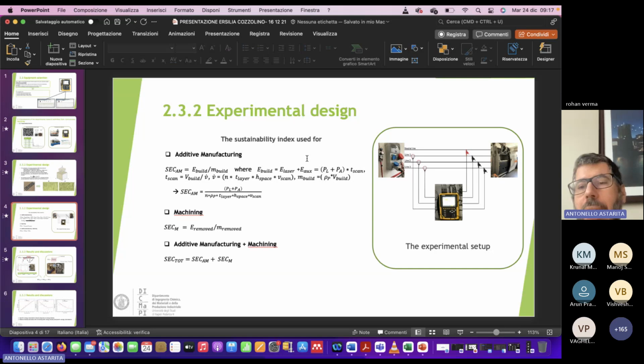So another good point is trying to reduce the processing time, because by reducing the processing time, you both increase the productivity of your system and decrease this amount of energy. Again, you can calculate these two amounts as the power required by the laser plus the power required by the auxiliary system, both of them multiplied by the scanning time, so the production time. But how to write down the scanning time? The scanning time can be seen as the ratio between the volume of your build and the velocity, that can be written as the number of layers multiplied by the time required to print each layer, the hatch space, and the scan velocity.